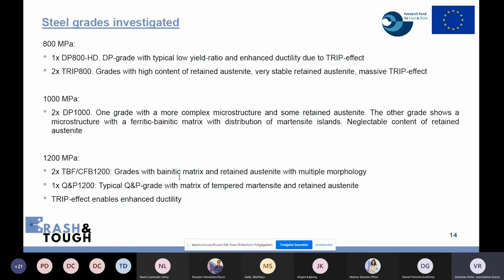And then we had the class with 1200 megapascal, where we had 2 TBF/CFB grades with different yield ratio. These grades had a bainitic matrix with retained austenite in multiple morphologies. And we had 1 Q&P grade with very high yield ratio with a matrix of tempered martensite and some retained austenite. And all the grades in the class of 1200 megapascal had a TRIP effect, which enabled the enhanced ductility.